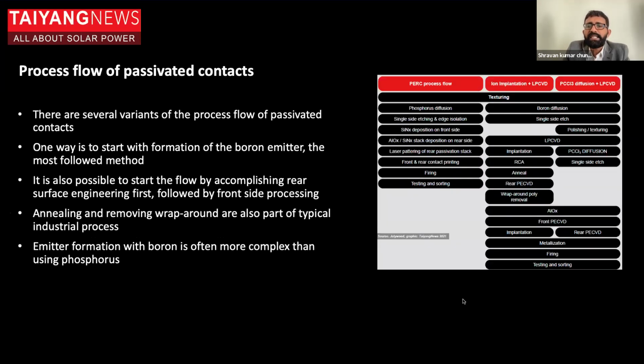So there are actually several variants of the process flows for the passivated contacts. So depending on the equipment, also the philosophy of the process. So the flow chart here, what you see, it is from the Jolywood, basically comparing, benchmarking it against with PERC, and Jolywood has been presenting two process flows. So one is based on ion implantation, another is POCl3 diffusion. And of course, as far as the main process, they have been using LPCVD based process.